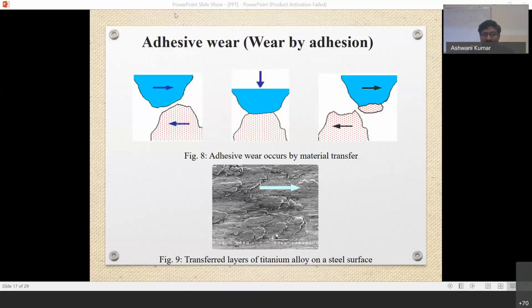In the figure, you can see there are different ways the wear appears. The deformation of a transferred material results in a layered surface morphology on the contact surfaces. This is the picture where we see a transferred layer of titanium alloy on a steel surface, forming a layered surface morphology. It is a transferred layer probably when the bond between the layer and the underlying material has been locally weakened by cyclic loading. So this is the morphology: a plate-like morphology will occur when there is adhesive wear.